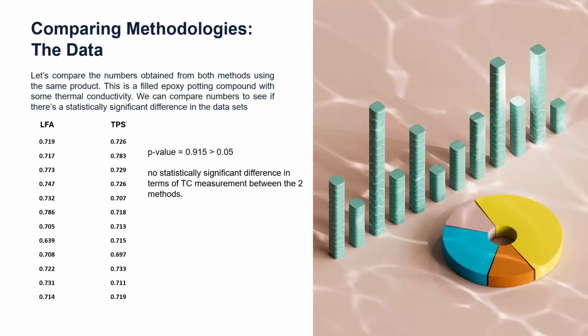And then finally, here we took a thermally conductive material, and we just compared the two methods. Looking at the data, if we run a two-tailed student t-test, we end up with a very high p-value, much greater than the 0.05 threshold that was typically used. So we can conclude that there's no real statistically significant difference between the measurements using the two methods. So we're very confident that our transition to the TPS method has not in any way compromised the data that we have. So that's all I have to say.